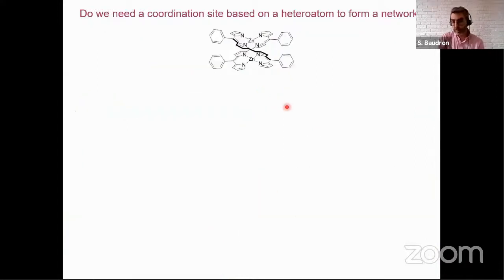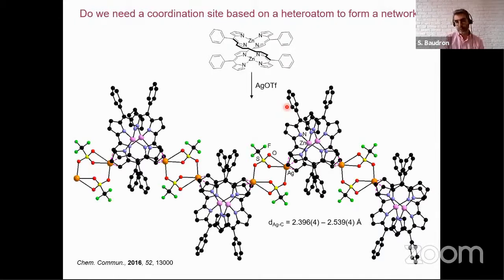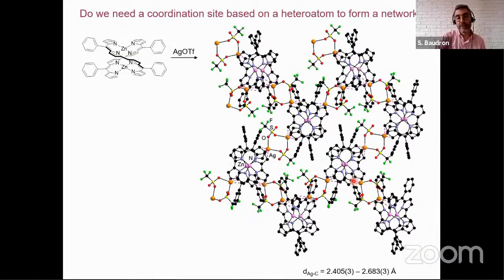So we went on to re-prepare this compound and studied its assembly with silver(I) cation. After a rather long time of optimization of the crystallization conditions, we were able to obtain a one-dimensional coordination polymer that is formed by complexation of a binuclear silver triflate unit via silver-pi interaction between the two strands of the helicates, thus forming this one-dimensional chain.